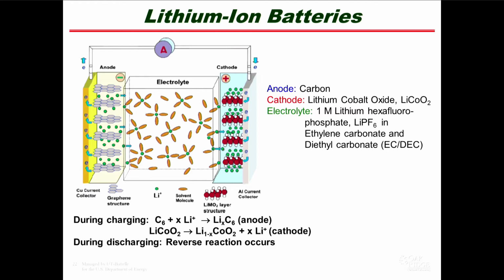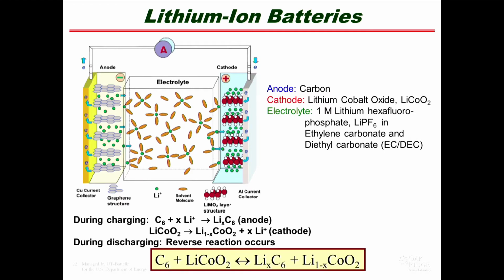When you do the charging, lithium comes out of the cathode, from the lithium cobalt oxide, as you can see in the equation on the cathode. The lithium goes through the electrolyte and is intercalated into the anode, into the layered structure. So you are transporting lithium during charging from the cathode through the electrolyte to the anode. To compensate this reaction, electrons go through the external circuit. During discharging, you are reversing the reaction. The net reaction uses graphite and lithium cobalt oxide, and that's what you typically have in iPhones, cell phones, iPads and laptops, all the batteries.